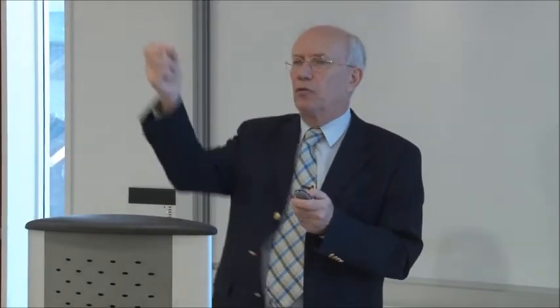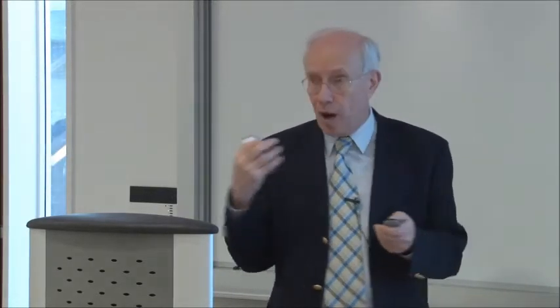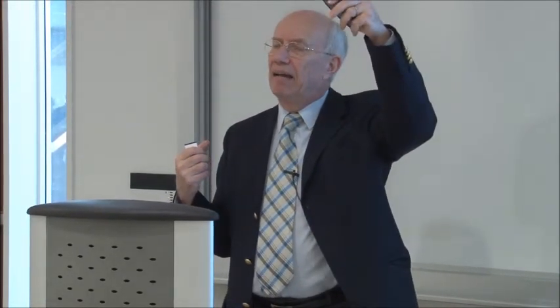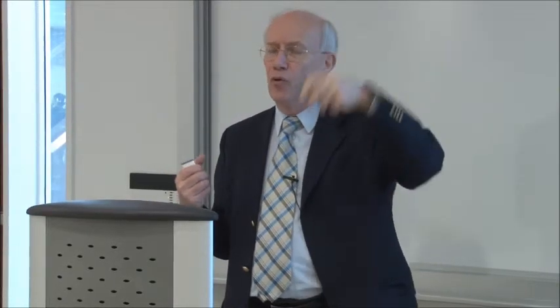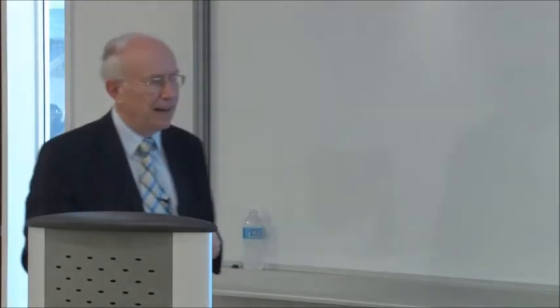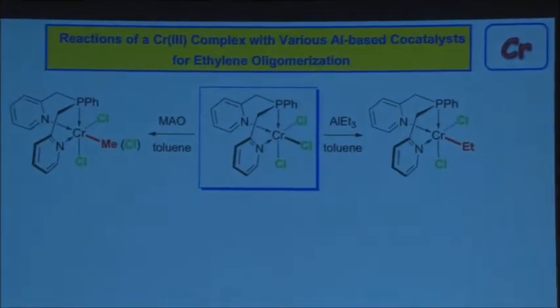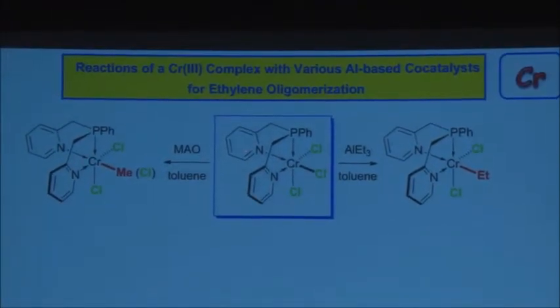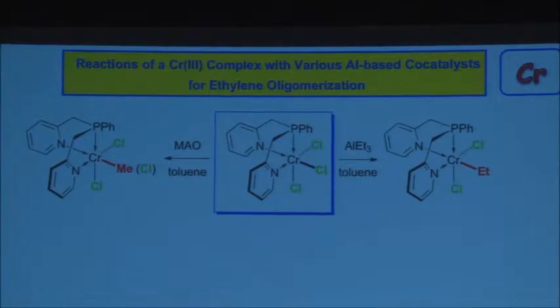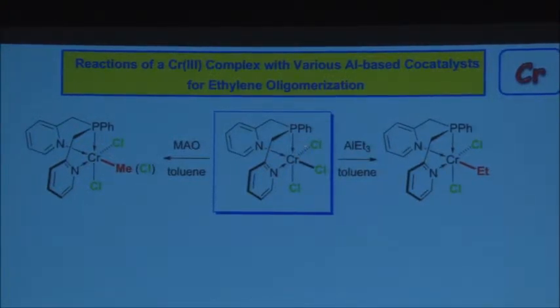Roughly speaking, as I said before, you need to create a metal-carbon bond in order for the ethylene molecule to insert into it. But you also need to make the metal center more electrophilic, forming cations. And that's often the property of the co-catalyst. By making the metal center more cationic, you increase the affinity of the ethylene substrate for the metal center. So roughly speaking, there are two key functions that the co-catalyst should have. But in detail, we don't always understand what happens. So I'm taking here just one example of a chromium-3 complex, which has here a tridentate ligand, 2-pyridine attached to a phosphine group in a facial arrangement in the octahedron, and 3 chlorides.